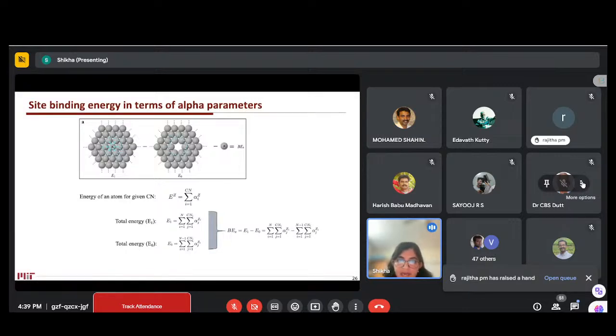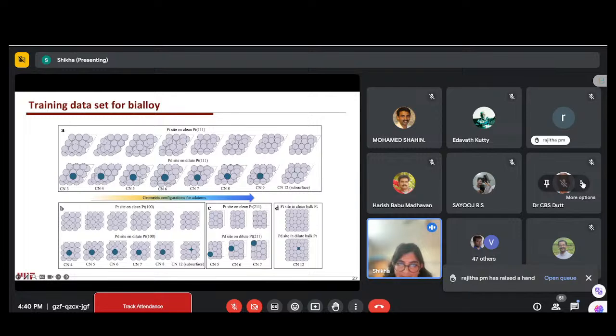Then we have two configurations: when we have the site here, and when we knock out the site from the surface. We calculate the energy from the alpha parameters, and we just take the difference of both configurations, and it gives us the binding energy of a central site. So this is the monometallic case.